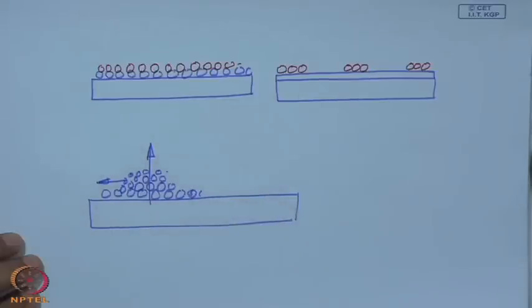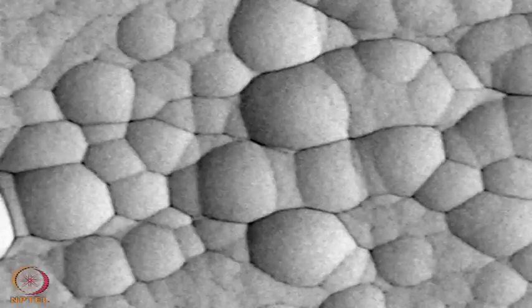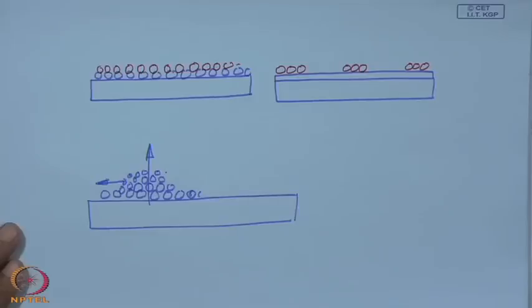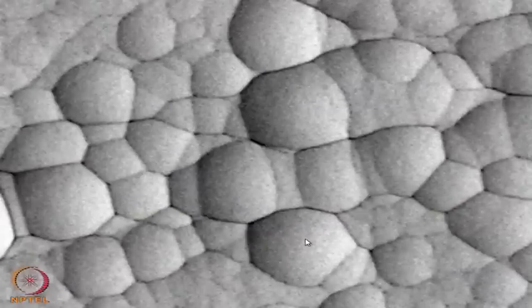So, these are the two ways it can grow, but obviously if we like to have uniform growth, then definitely it should be a uniform growth add-on process, not just selective sites where this add-on will keep on going. In that case, we cannot get a uniform coating, but we may end up with some outgrowth at different locations. So, this is one thing one has to consider. Now, this is one example of how this coating grows. Ultimately this is the top layer, and it is actually sphere like. We can illustrate this point here.